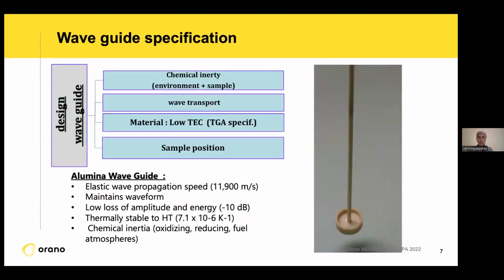If I show you the waveguide specification, it's a little bit complicated because the system has to be very inert, chemically speaking, to the environment and to the samples. It has to sustain high temperature, around 1000 degrees C, and it has to be very good for wave transport. This is a property of alumina: a very good elastic wave propagation speed and a low amplitude loss, because we generate the noise here at the bottom of the waveguide, and the wave will be transferred through these alumina tubes to the top of the system. So it was a huge work to define and design this waveguide, but finally we succeeded.